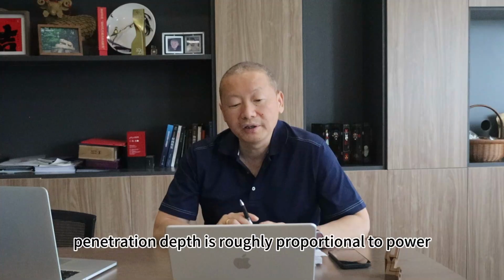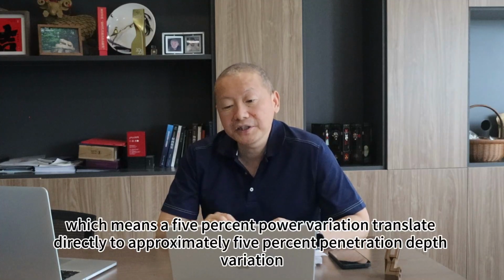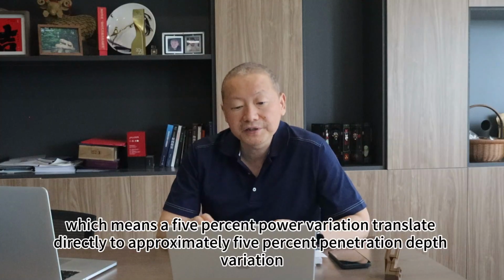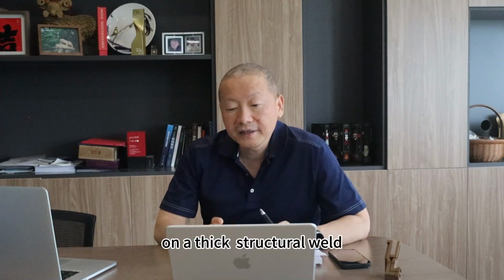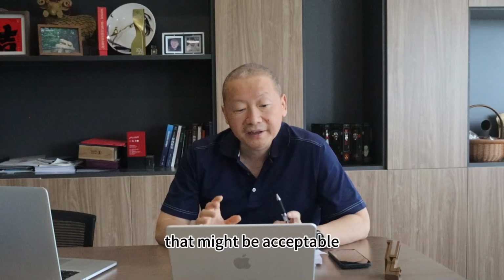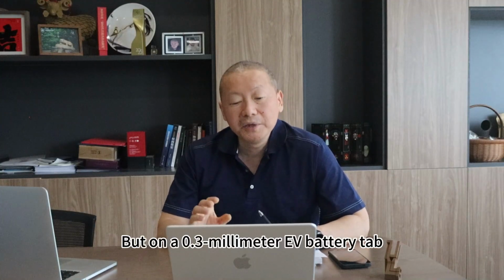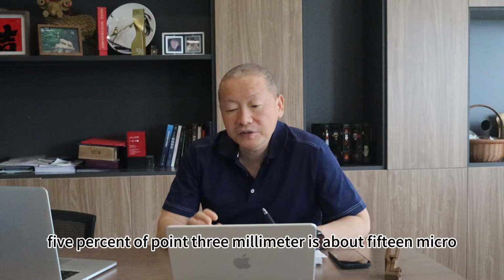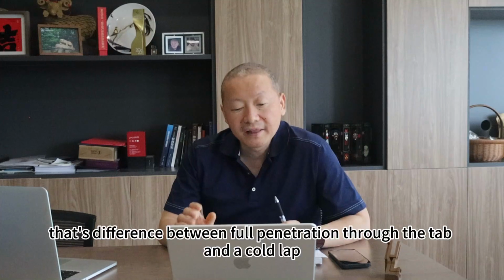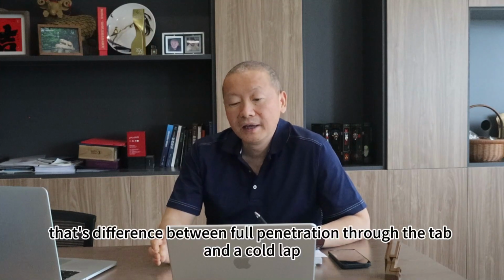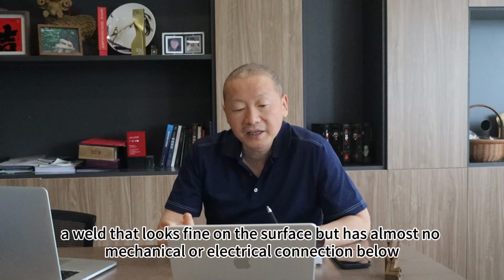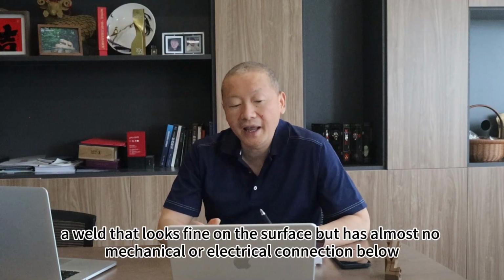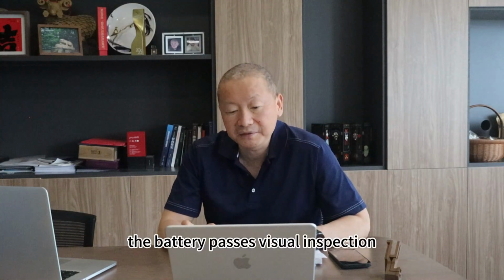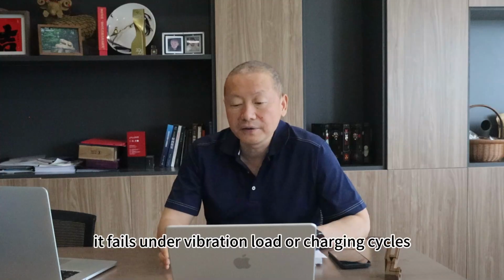First, power stability. In a steady-state keyhole, penetration depth is roughly proportional to power, which means a 5% power variation translates directly to approximately 5% penetration depth variation. On a thicker structural weld, that might be acceptable, but on, let's say, a 0.3 millimeter EV battery tab, 5% of 0.3 millimeter is about 15 micron. That's the difference between full penetration through the tab and a cold lap. A weld that looks fine on the surface but has almost no mechanical or electrical connection below. The battery passes visual inspection. It fails under vibration load or charging cycles.